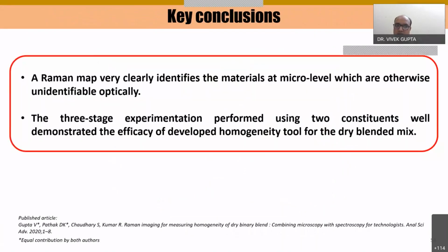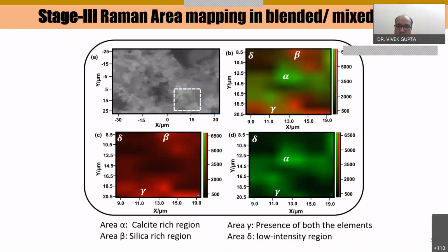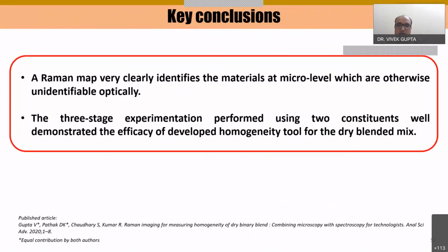So from our Raman map, we can conclude that a Raman map very clearly identifies the material at a micro level, which are otherwise unidentifiable optically. You have seen in the first image, that is the optical image, we could not identify which material is present at which place. So the three-stage experimentation performed using the two constituents well demonstrated the efficacy of the developed homogeneity tool for the dry blended mix. However, it can be further extended to the wet blended mix.